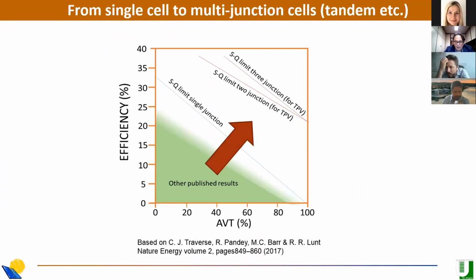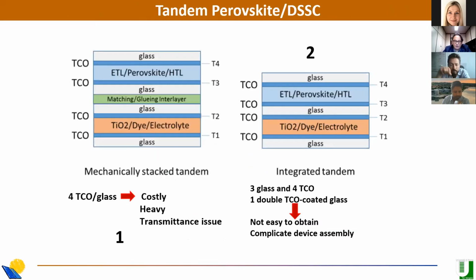So the idea now is to move from single junction to multi-junction, because in this way we can improve the efficiency. In the single junction, we are limited by the Shockley-Queisser limit. But if we move to 2 junctions, 3 junctions, we can improve further the efficiency of the solar cell. So for this reason, we were considering a tandem, a top perovskite cell and a bottom, for example, organic solar cell, with different configurations and also optimizing, reducing the number of interlayers to reduce the parasitic losses.